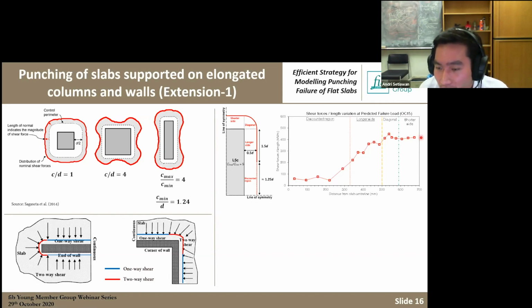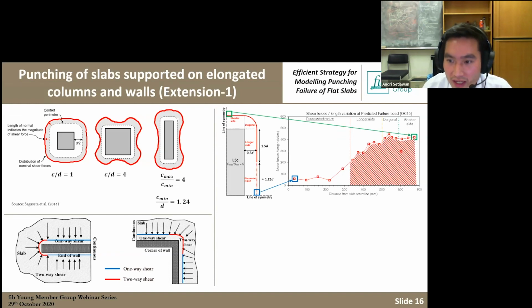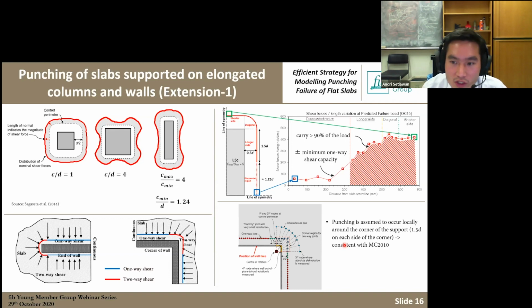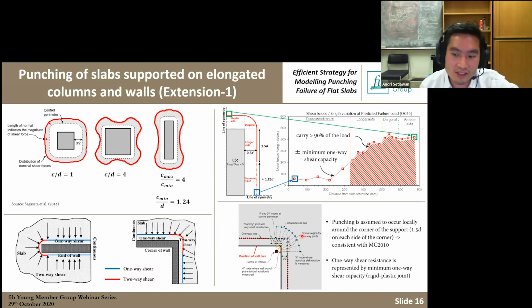We can see that the majority of the load is carried by the longer side, diagonal, and shorter side, and only the minority of the forces is carried by the disconnected region. This is showing here, yeah? So the dot in here represents the line of symmetry, and then this one represents the shorter side. When we integrate the force, we found that 90% of the load is carried by this two-way region, and only the minimum shear is observed elsewhere. So we modified the model with 2 assumptions. We assume that we only put punching joints along the corner, and then we treat the resistance of the one-way shear with a minimum shear resistance with a rigid plastic joint. So this is just a very brief overview of the extension that we did.